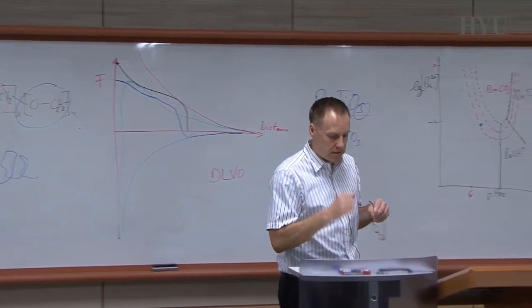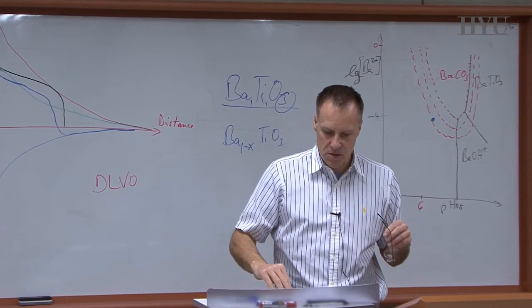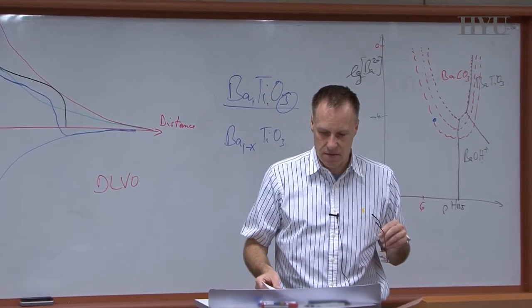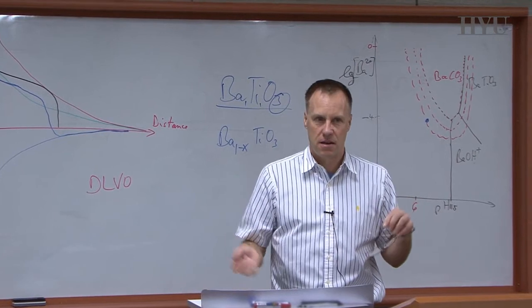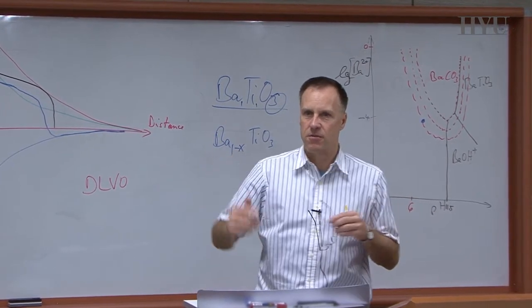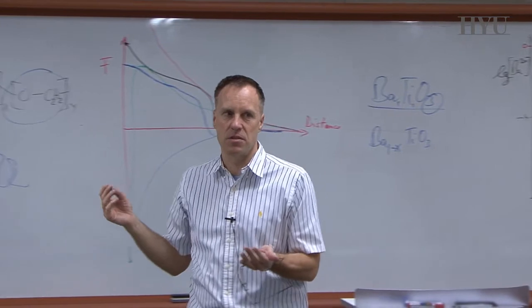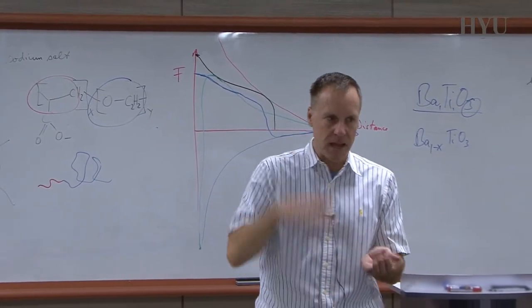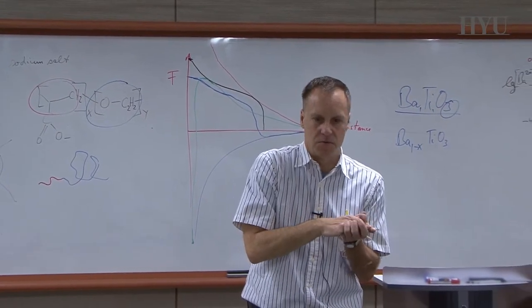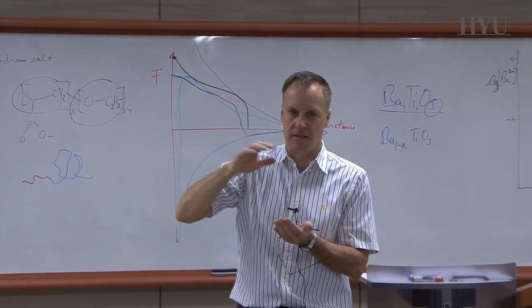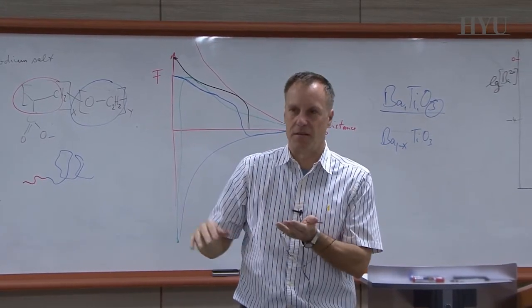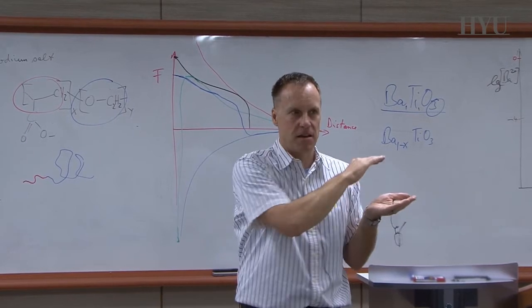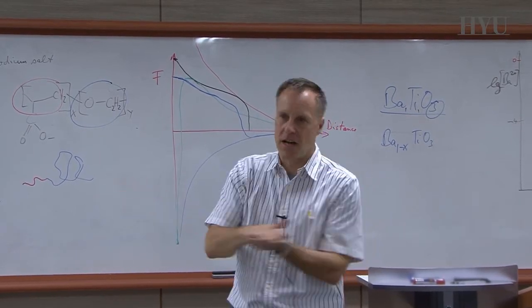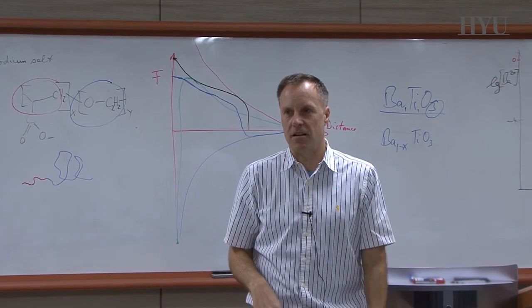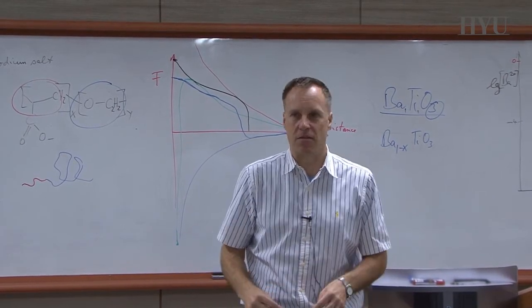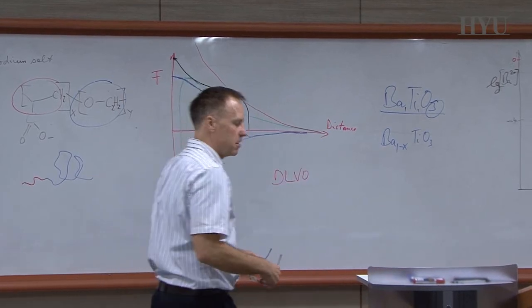That you can make it to high dielectric constants. And the other problem, of course, with all these things is they're very slow vacuum techniques. It's a layer-by-layer deposition. So if you want to make 500 layers, which is done in industry for the tape casting and stacking, you run really into the problem with the sputtering techniques. Basically you have to put down a barium titanate layer, then a platinum layer as an electrode, barium titanate, and it's just, yeah, for a few items it takes forever already. So it's not feasible to make it on a large scale.